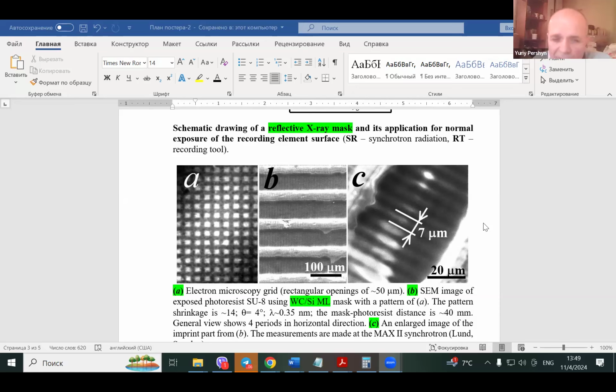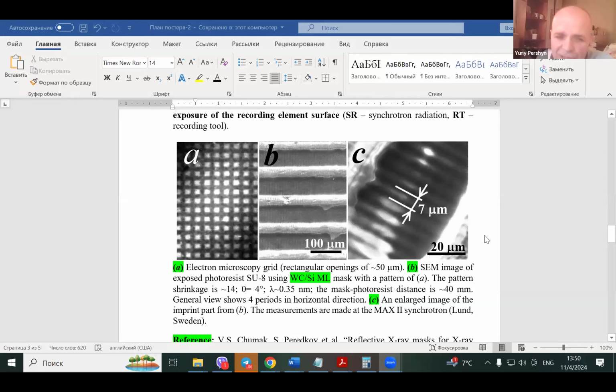At 4 degrees grazing incidence for synchrotron radiation, we get compressed image, which is shown on figure B, and magnified image of the part of the B is presented in figure C, and we can see that several microns of elements can be resolved in the resist plane.